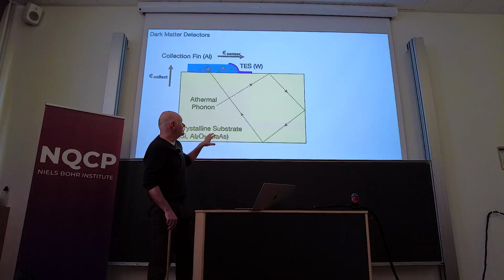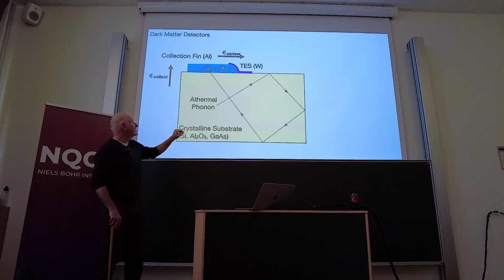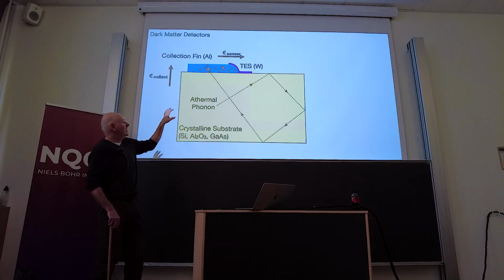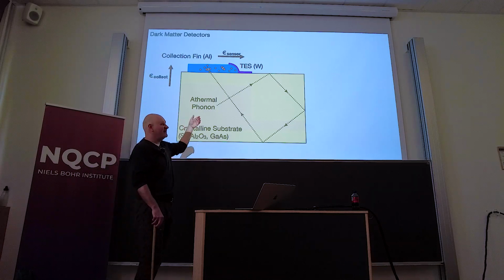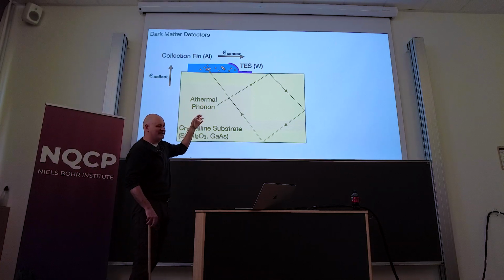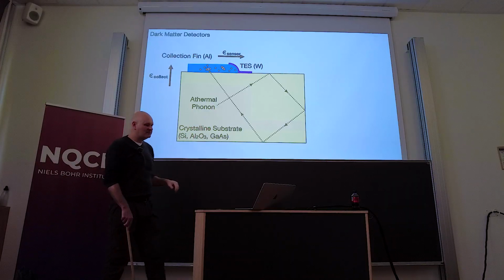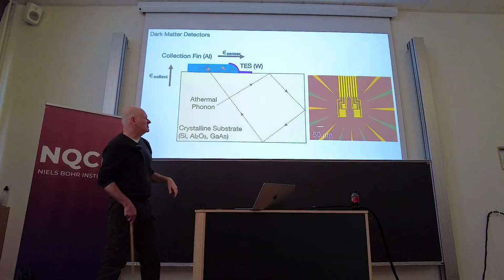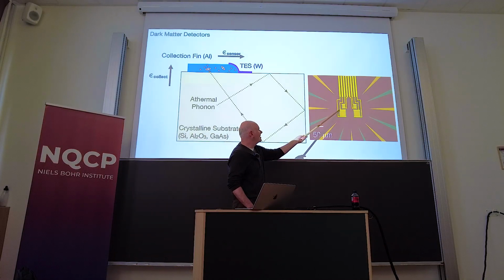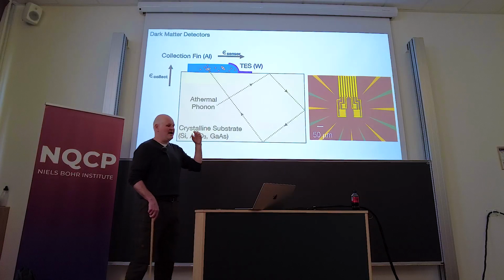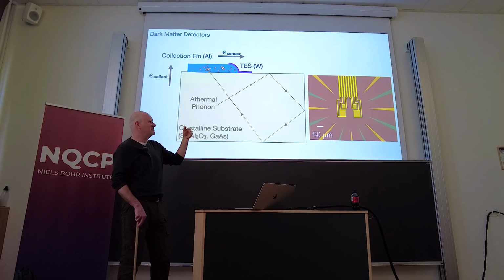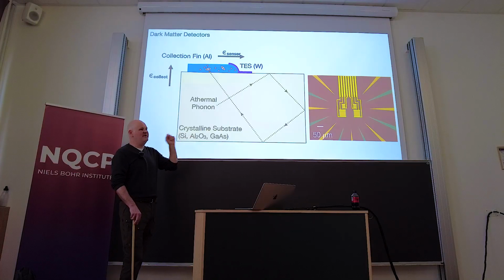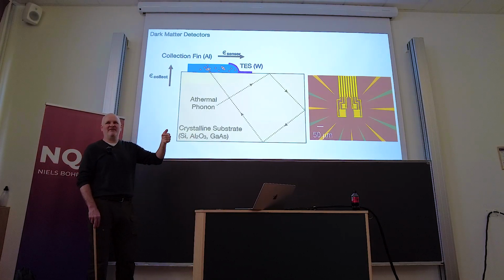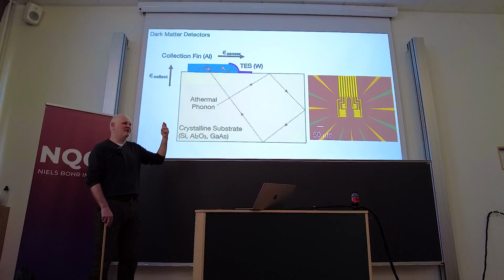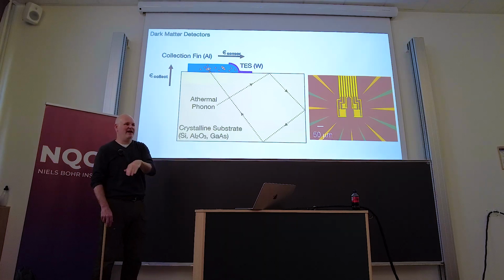And so the devices are essentially slabs of material, silicon, alumina, gallium arsenide, with essentially a transition edge sensor on the top. So there's a collection fin that collects the phonons and a transition edge sensor that detects when a phonon interacts with it. It looks something like this, where you essentially have these wires with contacts. These are all run at cryogenic temperatures, they're superconducting. When a phonon interacts with them, it breaks a Cooper pair, it changes the resistivity of the wire. That causes a thermal overload, which then breaks a lot of Cooper pairs. So it warms up, increases the resistivity, then it cools back down, and it goes back to superconducting.